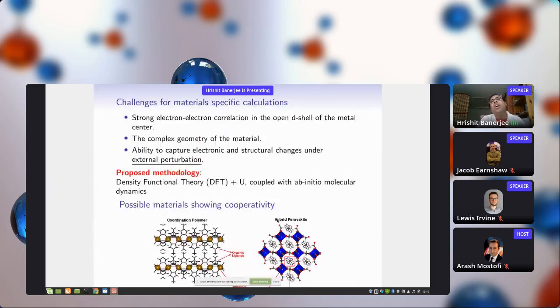So next we move on to real material calculations. And what are the challenges for these material specific calculations? Well, of course, strong electron correlation, because it is an open d shell, and then the complex geometry of the material. And we need to also capture the electronic and the structural changes under the external perturbation of pressure or temperature. And our proposed methodology is DFT+U coupled with ab initio molecular dynamics within the DFT+U regime.